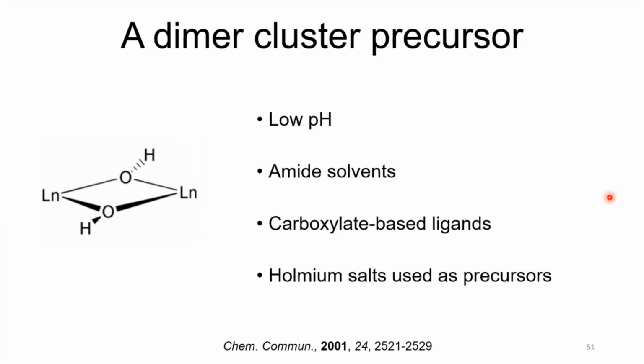So what happens is, when you first mix all of these, which you don't think is happening that much, what you're actually forcing is that these clusters start forming right away, because these conditions really favor these clusters. So once you make these clusters, then the MOF is built around them.